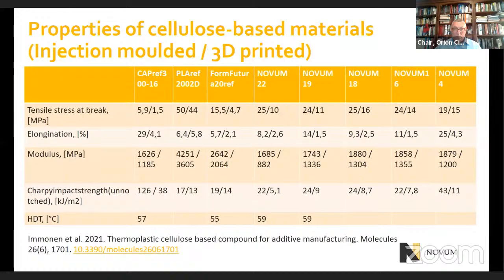Here are some mechanical properties measured both from the component that has been manufactured by injection molding and by 3D printing or additive manufacturing. And if we compare the Novum materials, there are 5 examples of those. They are comparable or better than the mechanical properties of commercial references, meaning, for example, this FormFutura. Some mechanical properties are better and some are a bit lower. For example, this modulus is something that we still face challenges with compared to commercial references. More details can be found from a recent publication where the reference is shown at the bottom of the slide.